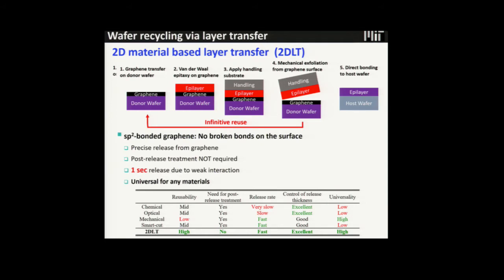Back in 2013, when I was working at IBM Research Center, I invented a method to get around this problem. We named the process the 2D material-based layer transfer process, which is as follows. We have a graphene layer on some donor wafer. Then you grow single crystalline epitaxial material on graphene on the donor wafer. As long as this is single crystalline material grown on graphene, you can easily separate the interface. You can easily peel them off, because graphene doesn't make any strong bonding to anybody. Graphene is a 2D material, so it's a slippery interface. Once you grow single crystalline material, you can peel it off. Then you can reuse the very expensive wafer on and on, as long as the graphene layer is there.